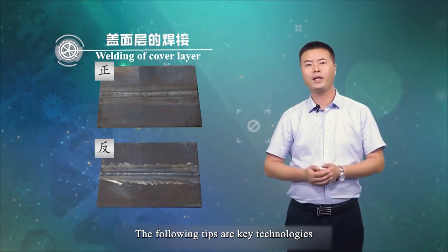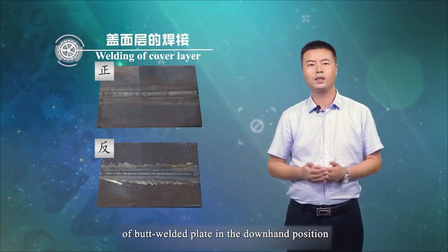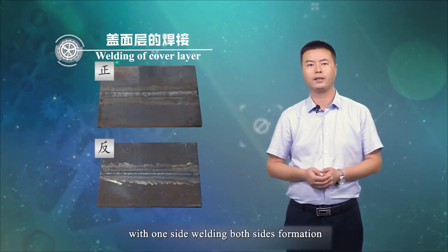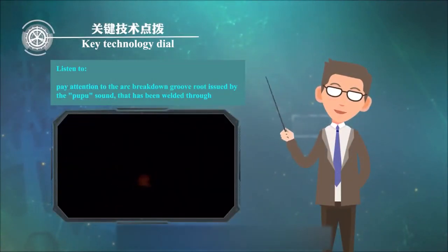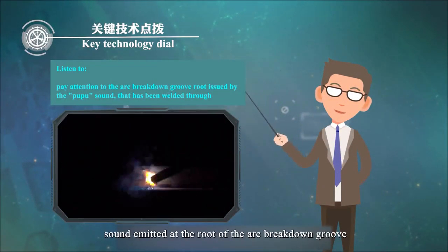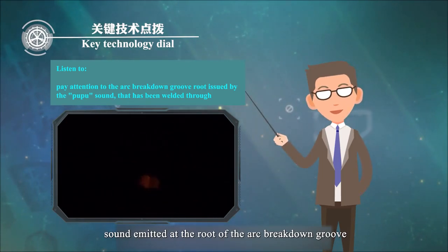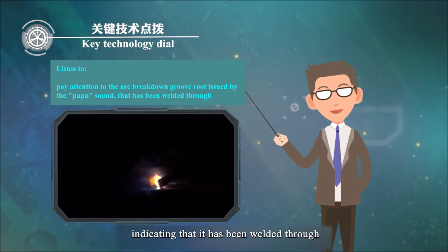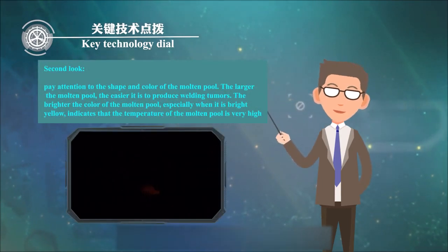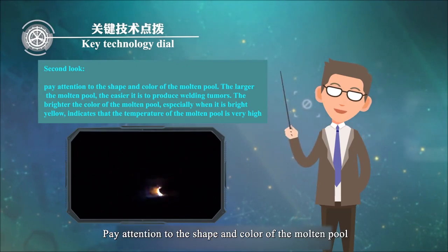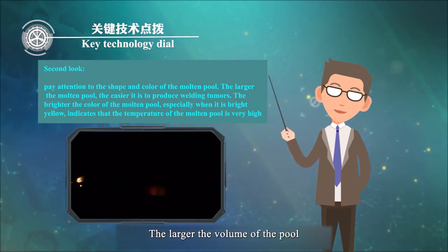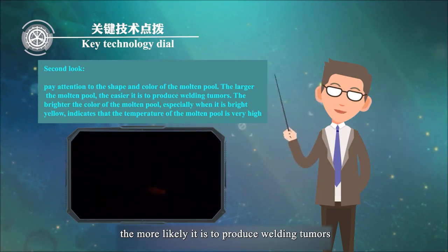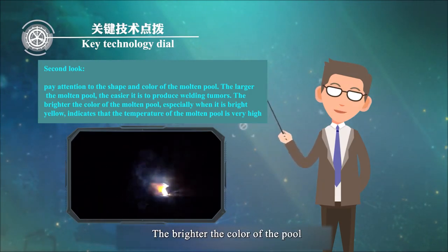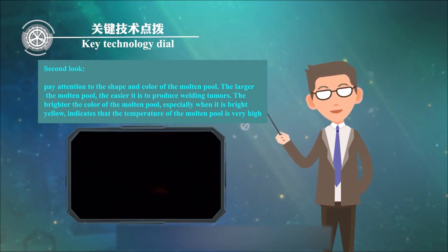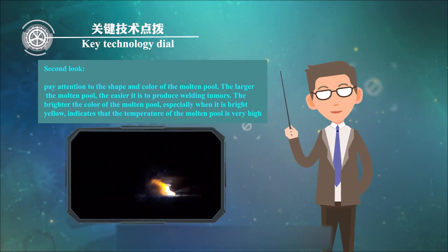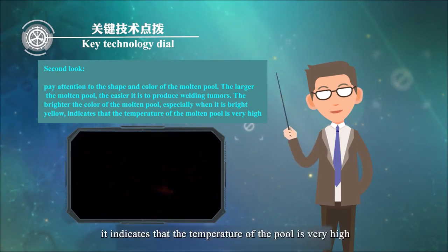The following tips are key technologies of butt welded plate in the downhand position with one side welding both sides formation. Firstly, listen. Pay attention to the pop sound emitted at the root of the arc breaking down the groove, indicating that it has been welded through. Secondly, observe. Pay attention to the shape and color of the molten pool. The larger the volume of the pool, the more likely it is to produce welding tumors. The brighter the color of the pool, the higher the temperature, especially when it is bright yellow. It indicates that the temperature of the pool is very high.